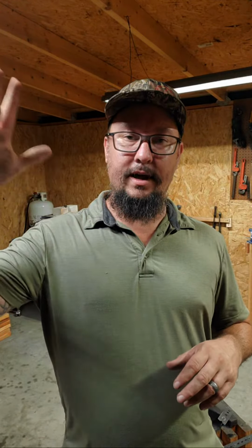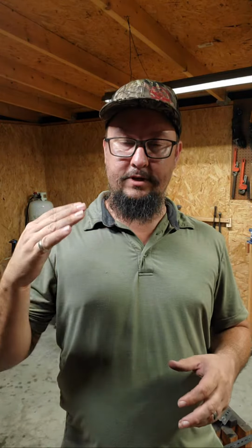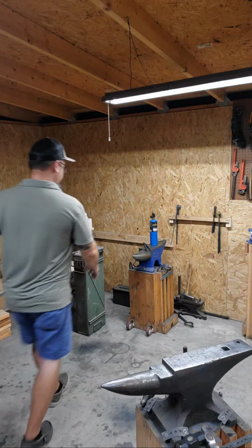The reason why I do my annealing process after forging is I want to relax the steel a lot, because we just, for one, put it through hell, beating the hell out of it. Plus, it was most likely a spring that was on somebody's car for a long time, so it had a lot of abuse. I want to take all that abuse out of it, and then I'll go through and do some profiling, things like that, and then I'll do my normalizing cycle, which is bringing it up to that 1600, letting it cool outside in still air, then bring it up to 1400, let it cool again. That's all I want. One normalize, one grain refinement, then bring it back up to 1525, quench that bad boy. Let's get it back in the forge.